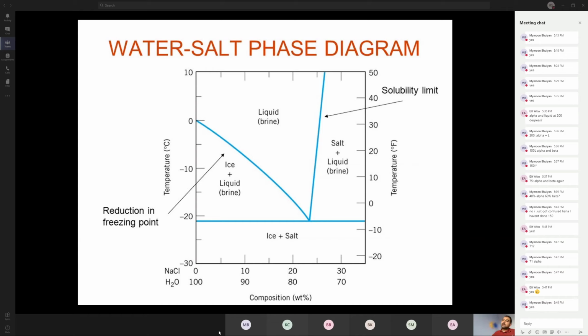Okay, here's a nice diagram. It gives you a nice simple explanation of something you've noticed before. Why do we spread salt on the roads during the winter? The reason is ice on its own melts at 0 degrees C. When you mix ice and sodium chloride, you get a eutectic. You'll notice this axis here is the concentration of sodium chloride. As I add more and more sodium chloride, the melting point of the ice decreases.